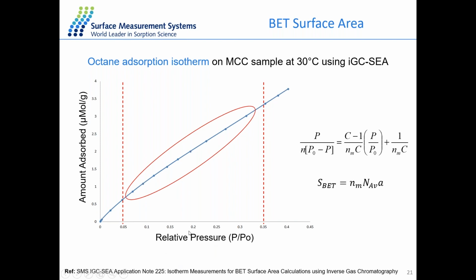So here we have the relative partial pressure above the surface, and we also have the amount of the vapor absorbed on the surface. Then we can convert this isotherm using this BET equation here. This equation is exactly the same as the volumetric technique for the BET measurement as well. So with this equation, we can convert the isotherm into a BET line. And from the slope and the intercept of this line, we can then calculate the C constant, the sorption constant, as well as the Nm value, and that's for the monolayer formation. So from the monolayer volume and the cross-section area of the probe molecule we are using, in this case octane, then we can get the BET surface area of the material we are interested in.